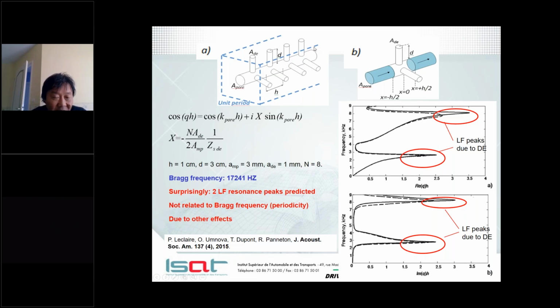So we did a simulation with typical values. You have the typical values here. With these values, we could see that the Bragg frequency, which is related to the periodicity of the structure, is 17 kHz, which is a bit too high compared to what we expected and what we observed. But also, surprisingly, in the dispersion curves, we noticed that there are two low frequency peaks predicted in this example, which are absolutely not related to the Bragg frequency, which is related to periodicity. So we have other effects, and we try to understand this because this was a very surprising, but also very interesting result for low frequency applications.